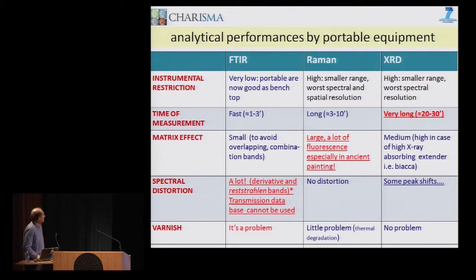And here I have reported a table where you can see the various instrumental restrictions for the three spectroscopic techniques that are most frequently used, besides Raman. X-ray fluorescence does not appear because I'm sure that you know everything concerning X-ray fluorescence. That is quite a standard technique and always works very well. Raman shows some instrumental restrictions: smaller range, and worse spectral and spatial resolution with respect to benchtop instrumentation. X-ray diffraction also offers a smaller range for the angular detection and the worst spectral resolution. Among the various instrumental restrictions, the lowest are those of FTIR, which is available today in portable instrumentation that offers performances close to those of a standard laboratory instrument.